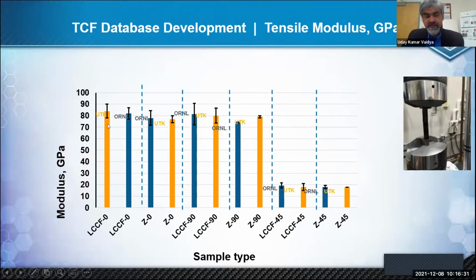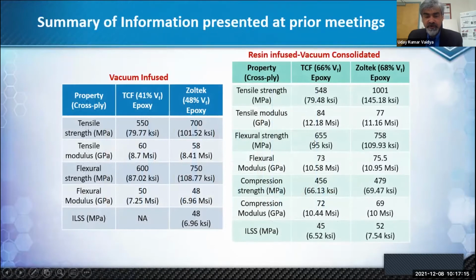You can see the modulus exceeds about 70 to 75 GPa, which is very comparable to that of Zoltek and other non-aerospace grade materials. The Z is the Zoltek fiber here in this case, which was also used as comparison. And we did this for different orientations, different cross plies as well as angle plies. And this has been systematically done for tension, compression, interlaminar shear, flexure, and impact testing. So that forms a good collection of properties with TCF in two different processes, vacuum infusion and compression molding. And this is just a table for more completeness for your review at some point.